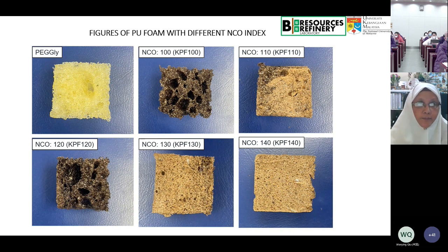Okay, so we're talking about the absorption. So this is the water absorption. You will notice that at 100, the absorption is very high. But at 120 and above, the water absorption is lower, which is very good as far as composite material is concerned. But for my application, I'm interested in the highest water absorption, because our end product is for agriculture.